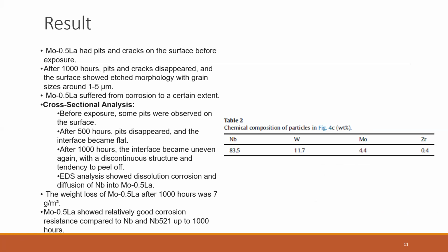For cross-sectional analysis, before exposure, some pits were observed on the surface. After 500 hours, pits disappeared, and the interface became flat. After 1000 hours, the interface became uneven again, with a discontinuous structure and tendency to peel off. EDS analysis showed dissolution corrosion and diffusion of niobium into molybdenum alloy.